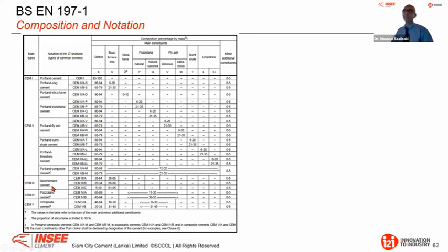After that you have the blast furnace slag cements, these are slag based. From 36, you can go for the C up to 95. This is exactly like you have in the C595, the type 1S up to 95%, according to ASTM. But here they have three categories. It is up to you. They give you the flexibility because you have to fulfill performance tests, compressive strength, heat, and so on. Therefore, the performance tests will put the boundary. They give you the whole flexibility, but the boundaries are there.